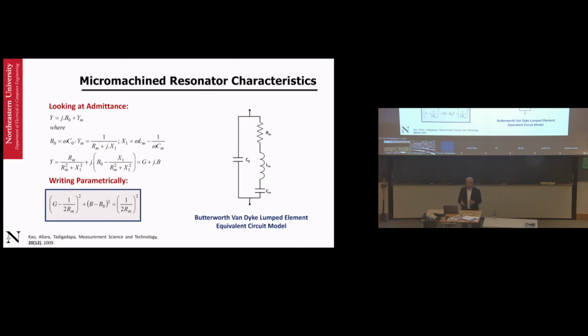If you take a quartz crystal and you start applying an AC field, you can actually excite acoustic resonances because it's a compression wave that is traveling through the material, or it could be a shear wave through the material. You have two boundaries, which is the two ends of a flat crystal, right? Start applying an electric field that is at the resonance frequency, and the thing starts to resonate. And that's how we have the quartz crystals running our watches, keeping the time for our computers, and so on and so forth. And so it's well known, right?